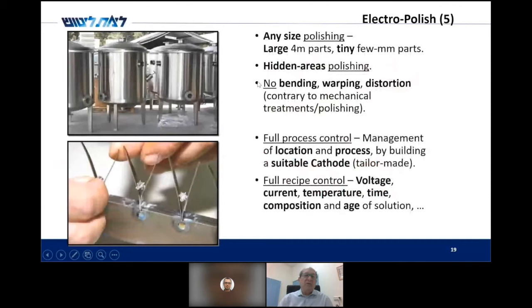You can electro-polish all sorts of sizes. These are very big chambers, and these are very small pieces. Between 4 meters to a few millimeters, we can electro-polish all sorts of workpieces. There's no bending, warping, or distortion, contrary to mechanical treatment, which is nice. We have full control of the process by locating correctly the counter cathodes, which are tailor-made to each case. And we fully control the voltage, the current, the temperature, the time, and the composition and age of the solution. So we have full control of this process.